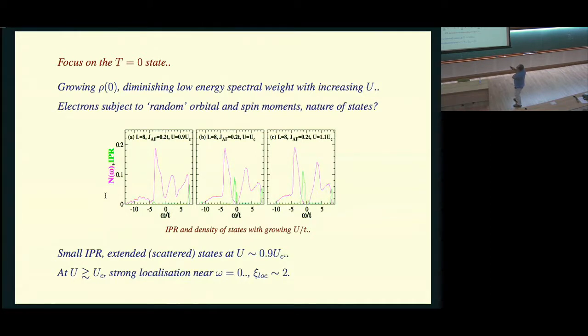Okay. If I go to 1.1 Uc or 0.9 Uc, I see IPRs which at omega equal to 0 are like 0.1, suggestive of a localization length of a couple of lattice spacings. So the combination of orbital and spin disorder in the vicinity of the metal insulator transition leads to electronic states. Within this picture, you can still think of single particle states which are extremely localized. And if you go to the insulator, they are even more localized, if you wish.